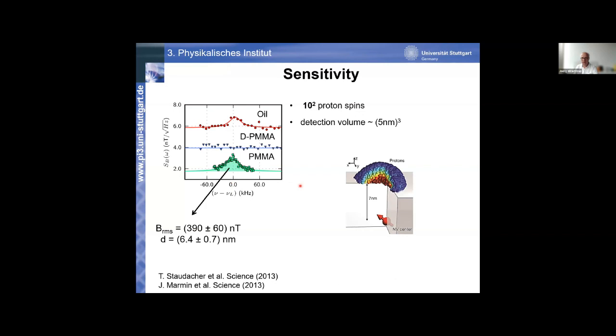Let me show you this. Specifically, the experiment is done such that we take NV centers. This is not scanning at the moment, but it's just one of these NV centers very close to the surface, a few nanometers. You put a drop of liquid on top of it, say water, and then you do this magnetometry scheme. You change your tau, that is, you change your sensing frequency, and lo and behold, at the frequency of the Larmor precession of proton spins, you see a signal.